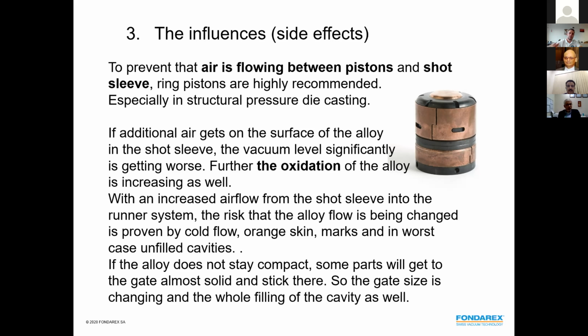So what is the result? We can see some orange skin, we can see flow marks. In the worst case, we can even see that the cavity didn't fill well in some areas, because some of the metal which has been sucked is getting semi-solid and doesn't fill some parts of the mold, the cavity, that well.